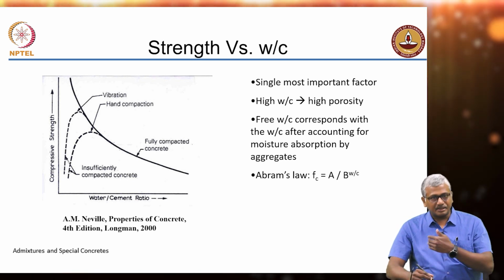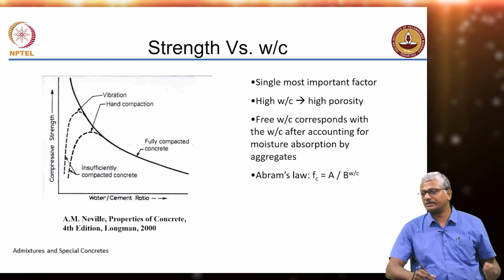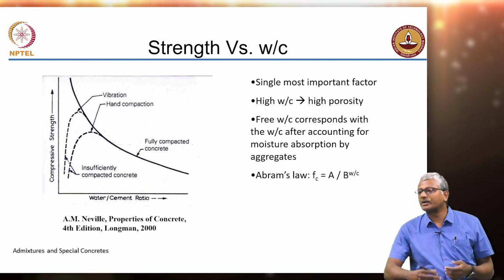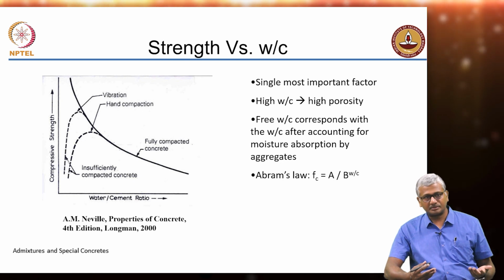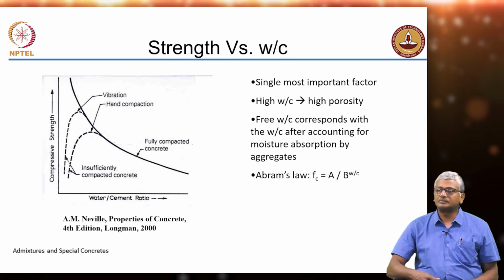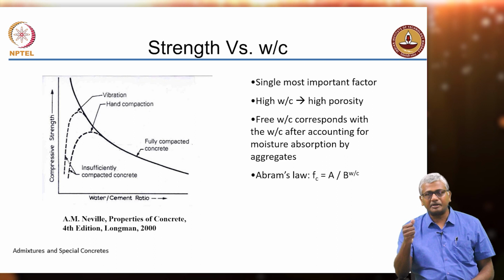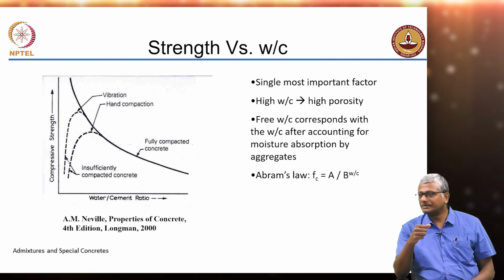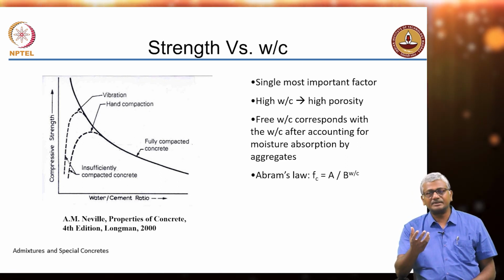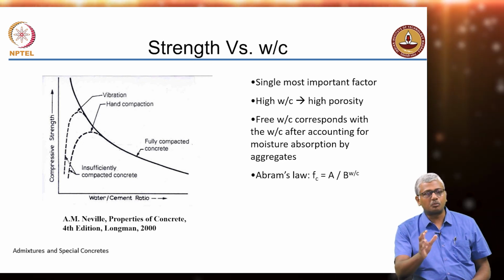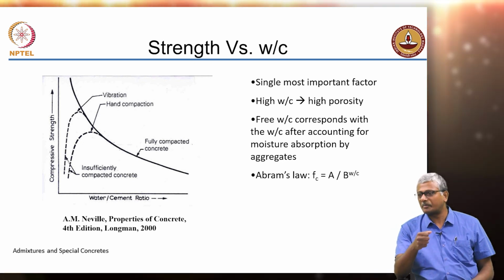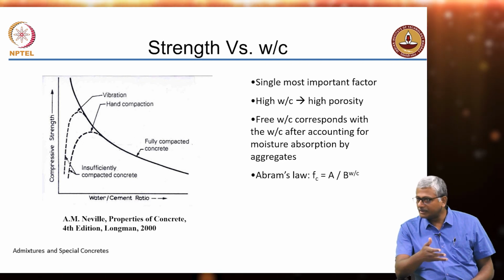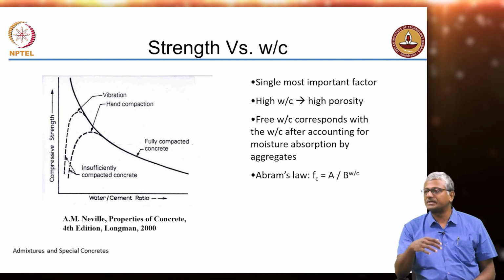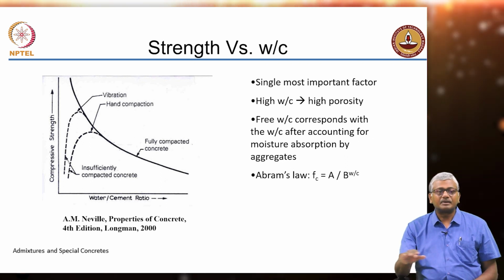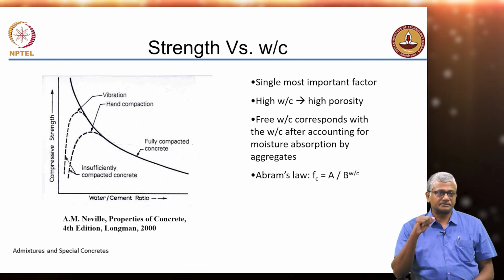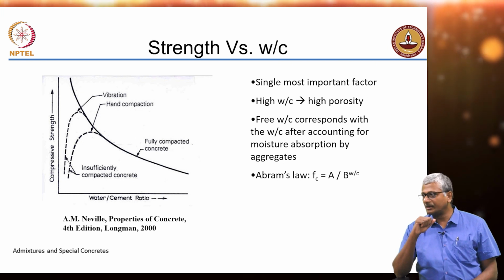So, technically the lower the water to cement ratio, the higher the strength, but there is a limit to it, because you cannot compact your specimen beyond a particular point, right. I do not know how many of you have actually made concrete in the lab and tried to compact it by hand, you will notice that if the concrete has a water to cement ratio less than about 0.4, you will not be able to compact by hand. So, at that limit, your strength will start going down because the degree of compaction will not be enough to completely avoid all the porosity or voids in the system, right.